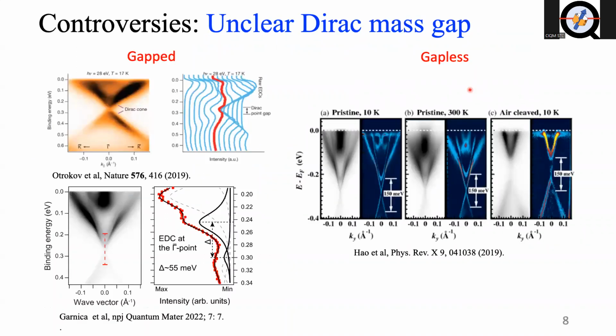And another controversy is the presence of the Dirac mass gap. As I mentioned in the beginning, the exchange coupling between the Dirac surface state and the magnetism should open up a gap. It breaks time reversal symmetry and opens up a gap at the Dirac point, which is a prerequisite for the presence of the quantum anomalous Hall effect. However, even this requirement is still under heated debate. So it's not clear yet.